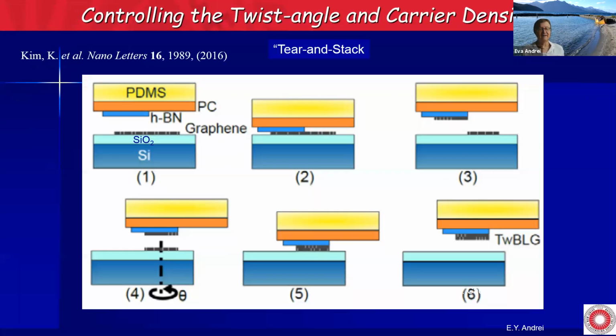So you prepare a standard graphene on silicon dioxide, then you bring a boron nitride layer, you press a boron nitride layer on half of the sample, and you have to adjust the temperatures, so half of your graphene sticks to the boron nitride. You lift the boron nitride, it tears apart, and now you have two graphene layers that are part of the same crystal. You rotate the bottom crystal by an angle which you can control to a fraction of a degree, and then put your top layer on top of it, and then you remove the two, and voila, you have a twisted bilayer graphene. And of course, after that, you have to deposit electrodes and whatnot.